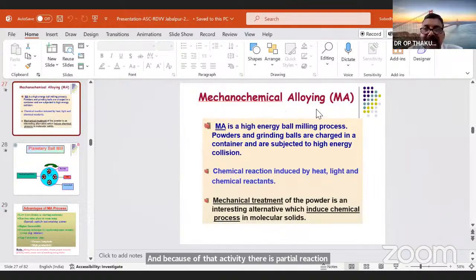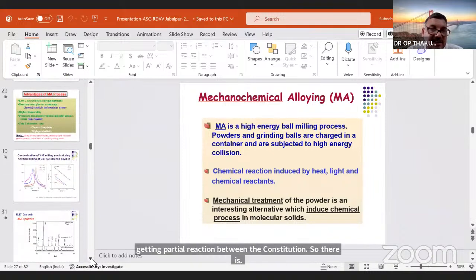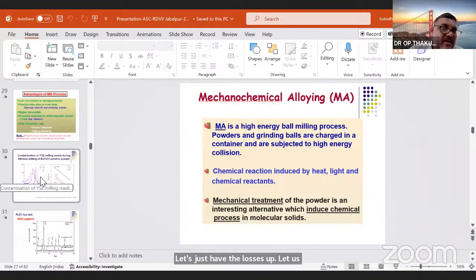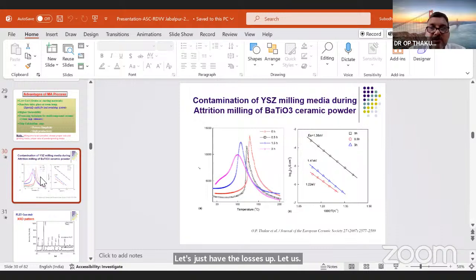That's why mechanochemical alloying is a very good technique to deal with highly volatile constituent ceramic compositions, like lead oxide based constituents, bismuth oxide based constituents. Because in this process, at room temperature itself, you are getting partial reaction between the constituents. So there is less chance of loss of lead oxide as a component.